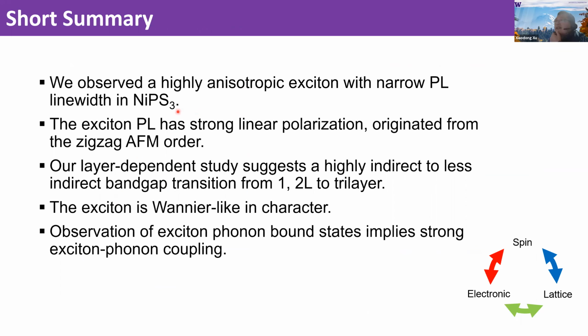Okay, so in conclusion, we observe highly anisotropic excitons with narrow linewidth in nickel phosphorus trisulfide. The exciton has a strong optical anisotropy, which is linearly polarized, and we demonstrate it's coming from the zigzag antiferromagnetic order. And we show this exciton has a strong dependence on the layer thickness, which indicates there are electronic structure evolutions with the layer thickness. And lastly, we show there's a very strong spin lattice coupling effect from these exciton phonon bound states. So hopefully I convinced you that nickel phosphorus trisulfide is an interesting candidate to study the strong coupling between spin, lattice, and electronic structure degrees of freedom. So any questions before I move on to the second part of my talk?